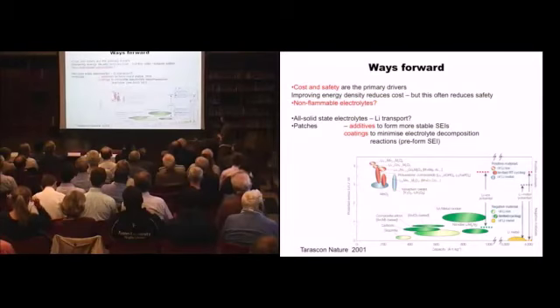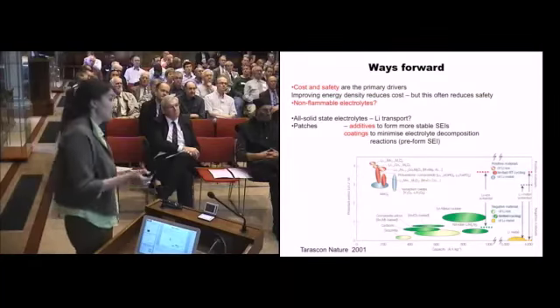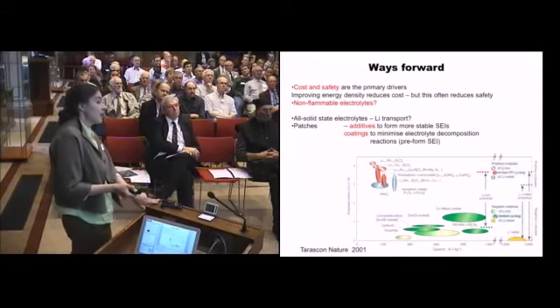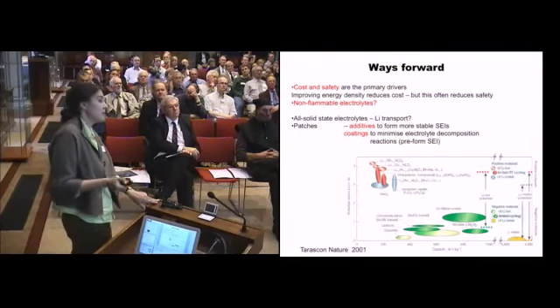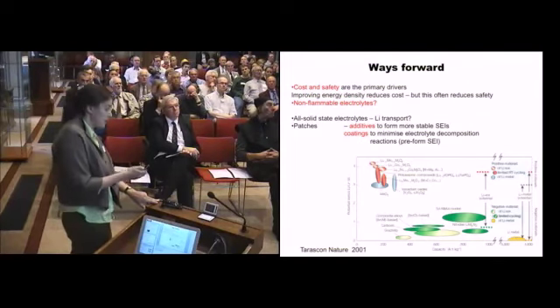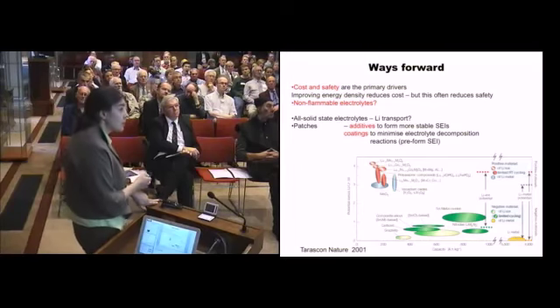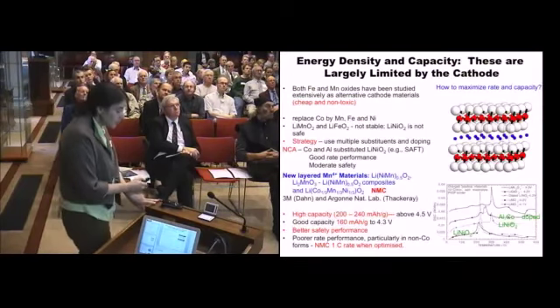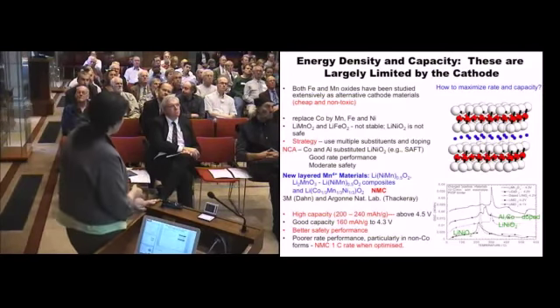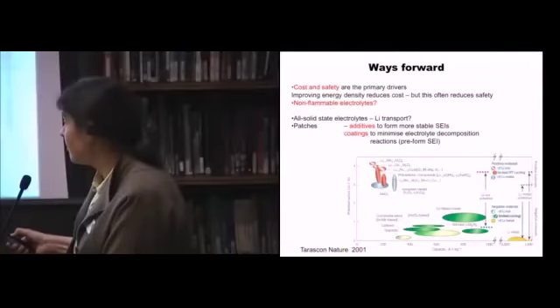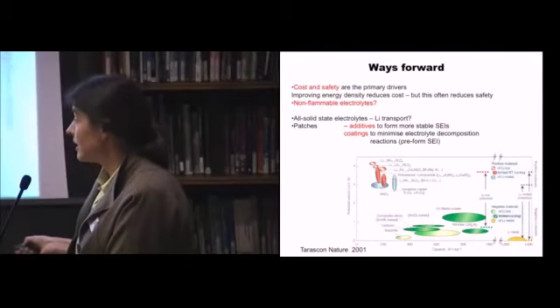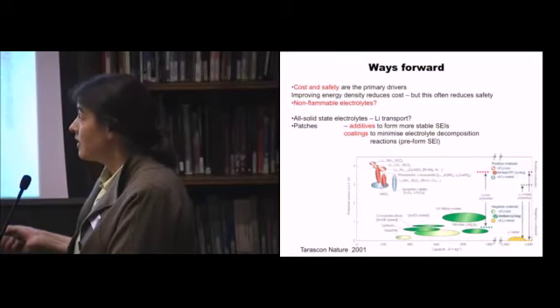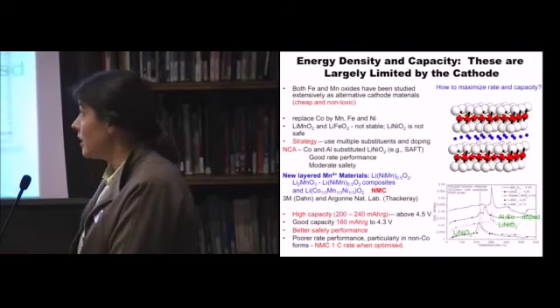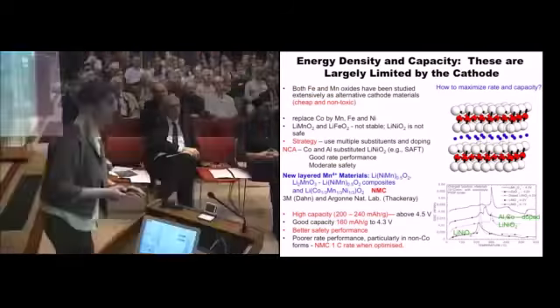And then we work on a whole variety of different materials that are out there that might increase the capacity over the materials that are available. So there's graphite here, and there's a whole series of other materials you can consider as anodes, and there are other materials you can consider for the cathodes, and this is what I want to talk about now. So the graphite has a capacity of about 375 milliamp hours per gram, so that's down here. So this is basically how many electrons you can get out. Lithium cobalt oxide is 120. So the limitation is really on the cathode.